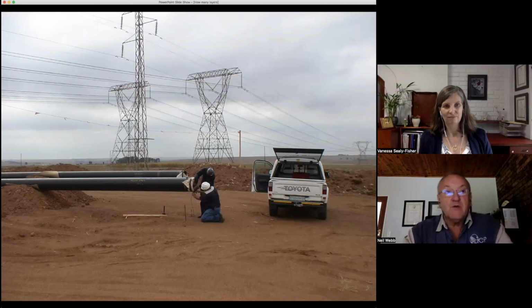And in this picture, this is taken during pipeline construction phase, when the pipes are above ground. You can see the proximity of those overhead power lines. And in order to prevent the operators from being shocked whilst working with the pipes above ground, because they've obviously got to weld them into a long string, pick them up, put them in the trench and so on, these pipes are being earthed with a temporary earth connection in order to discharge, in this case, any capacitive interference.